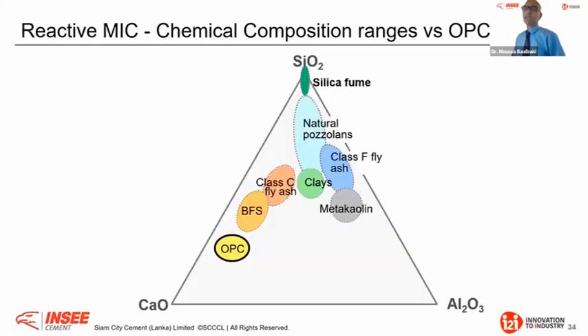Now, chemically, when I look at those products and put them in a ternary system, that is calcium oxide for the basicity, and aluminate, you see here what you have. You have the latent hydraulic product, OPC, with a basicity always above 2; blast furnace slag, where a good one will be over 1; and C-fly ash, from bituminous or lignite coal, mainly found in the States and very little in Germany. They also have a certain basicity, above 0.5. Therefore, these are the latent hydraulic, this is really the hydraulic one.